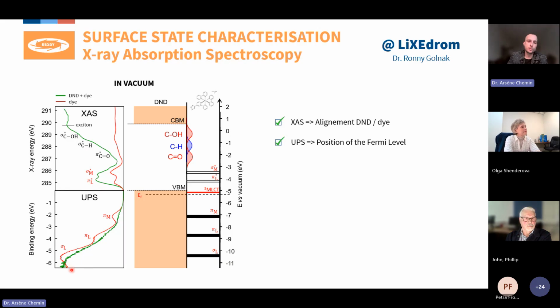And here, once again, we find the emission coming from the valence band of the diamond. And on top of it, you have those three features here that correspond to the occupied state of the dye. And we can also measure the Fermi level that is just below the 3MLCT state, which is a metal-ligand state in the dye, which is unoccupied. So when everything is dry, the Fermi level lies below here.